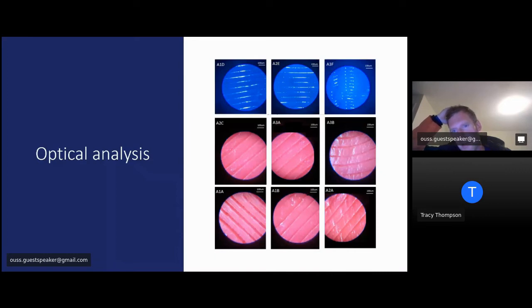The fibers are quite neatly placed together. The scale there is about 100 micrometers for the width of the bead. So it's quite small, but not too small. The sample numbers are basically the extrusion tip distance on the base of the plates that's being printed. Sample A1A, the bottom left one there, you can see that the beads look quite elongated, and that's probably just due to the placement of the fibers onto the extruded bed.